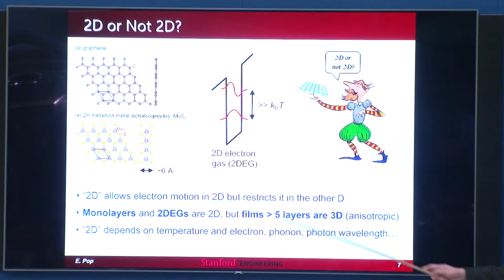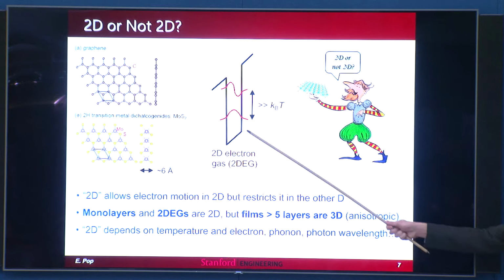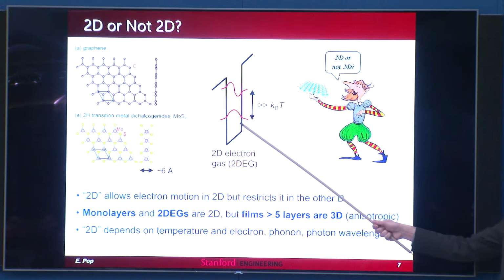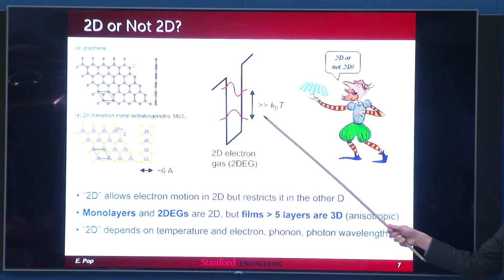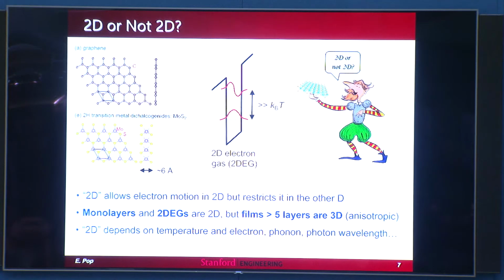And the usual definition is that the spacing between the energy levels that appear in quantum wells is significantly greater than kT. So of course, electrons will basically be confined in one of these energy levels, at most 2, and of course, they cannot move out of plane. So by that definition, actually, if you look at 2D materials, probably anything more than 5 layers is probably kind of a 3D material, just an anisotropic 3D material, as we'll see in a moment. The other thing I want to point out is that the 2D-ness of something probably depends on temperature. Actually, not probably, definitely depends on temperature. And a material could be 2D for electrons, but 3D for phonons.